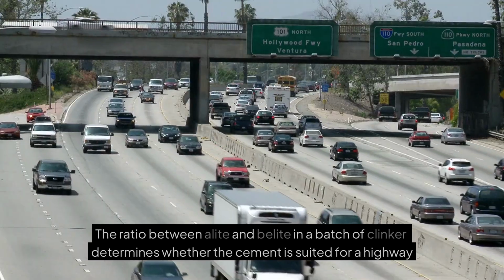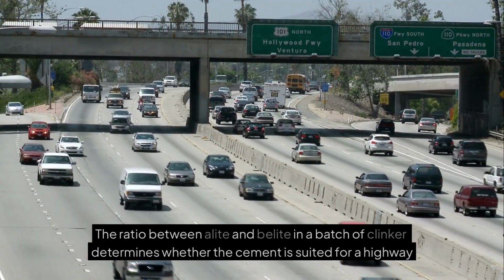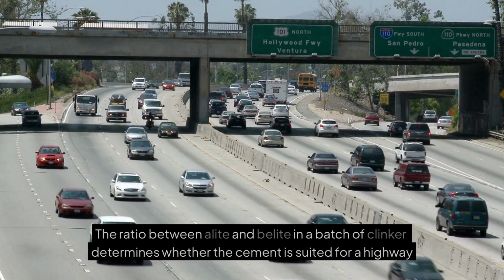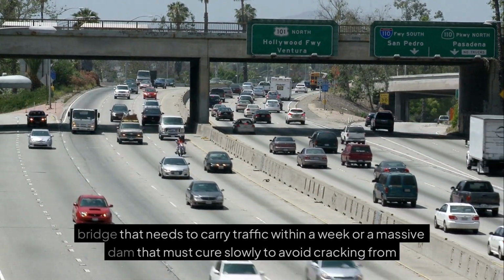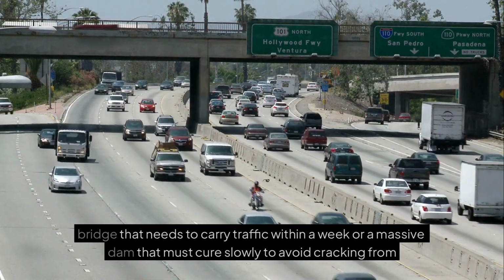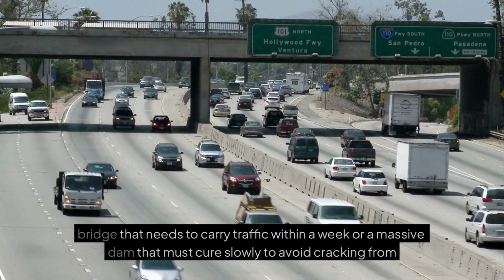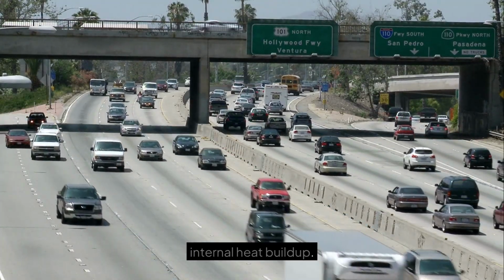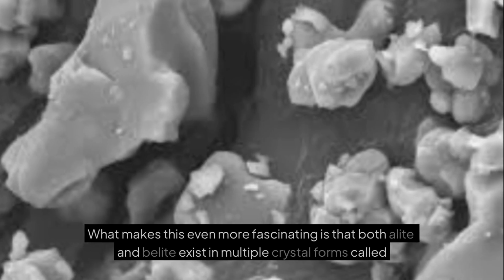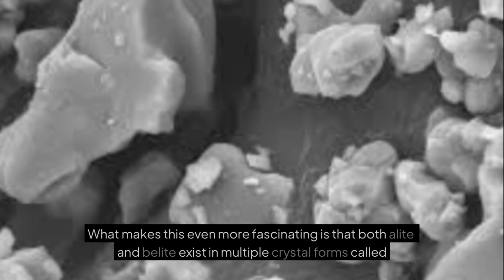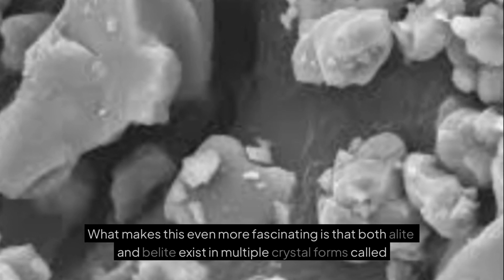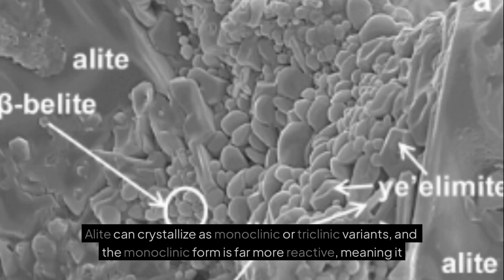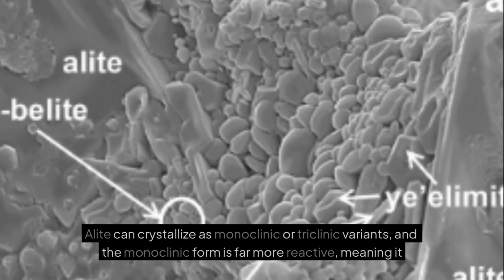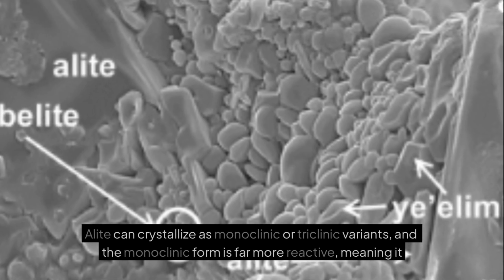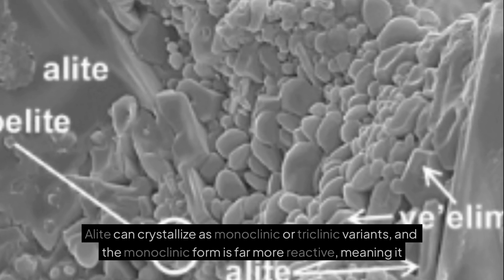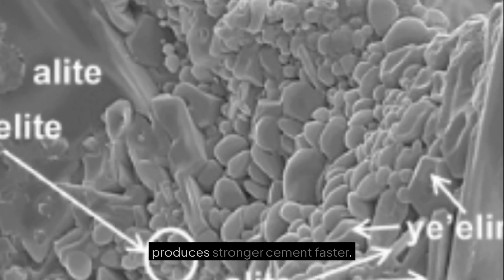The ratio between alite and belite in a batch of clinker determines whether the cement is suited for a highway bridge that needs to carry traffic within a week or a massive dam that must cure slowly to avoid cracking from internal heat buildup. What makes this even more fascinating is that both alite and belite exist in multiple crystal forms called polymorphs. Alite can crystallize as monoclinic or triclinic variants, and the monoclinic form is far more reactive, meaning it produces stronger cement faster.